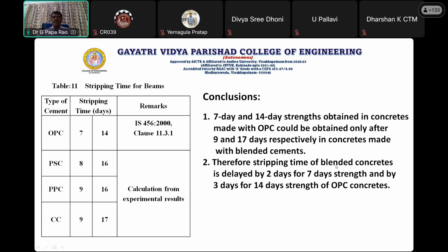So the conclusions we have drawn from our study are that the 7-day and 14-day strengths obtained in concretes made with OPC could be obtained only after 9 days and 17 days in the others. Our stripping time for concrete made with OPC is 7 days, but if you use other blended cements like PSC, PPC, and CC, this time is delayed by another 2 days, to 9 days. Again at 14 days, the time is delayed by 3 days, to 17 days. So the stripping time of blended concretes is delayed by 2 days for 7 days and by 3 days for 14 days. These are the observations we have made from our study, arriving at the stripping time for concretes made with blended cements.